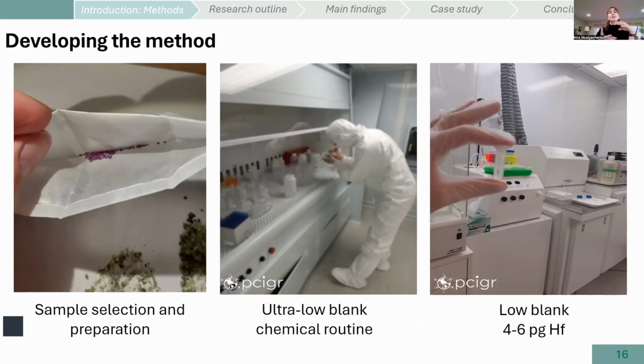To do so, I grind the sample in an agate mortar and pestle because I'm really scared of contamination since the levels are so low. And then I grind the sample to the size fraction of the mineral I'm interested in, and I pick it out. That way I prepare the aliquot of garnet, clinopyroxene if present, and then I make a whole rock powder. After that, all of those aliquots get dissolved in a mix of strong acids, and the tedious lab process begins, where we separate lutetium and hafnium from the rest of the elements that belong in our samples.